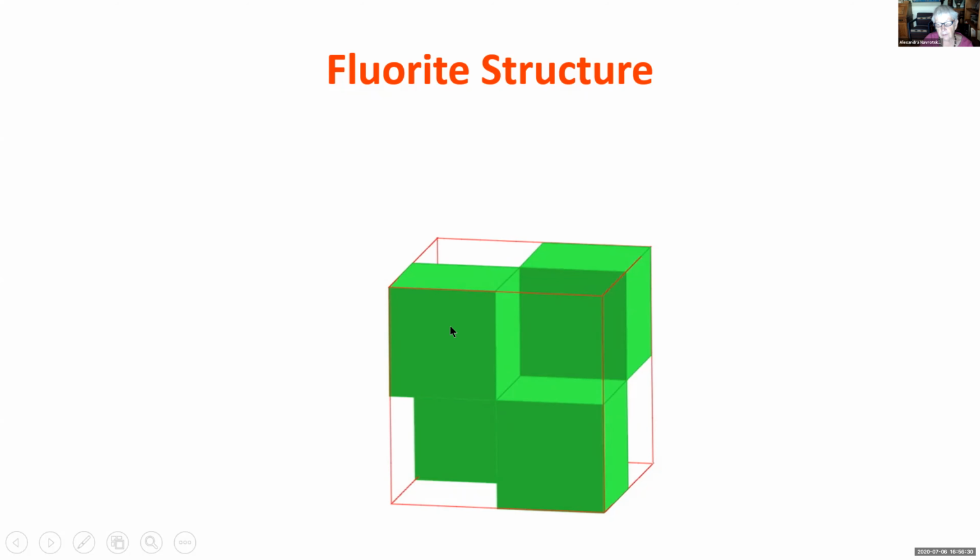In addition, then, one can have different cations in the central site from the cube. Well, again, once one starts doing these substitutions, the simple random cubic structure in which vacancies are arranged at random and substituents are arranged at random is generally not the most favorable configuration, except perhaps at very high temperature. And a very large family of derivative structures has been discovered and characterized really over the last 50, 75 years.